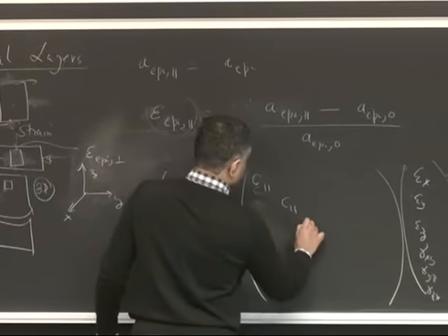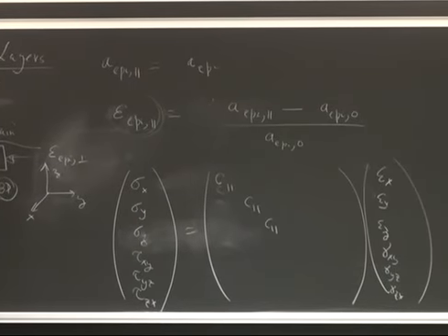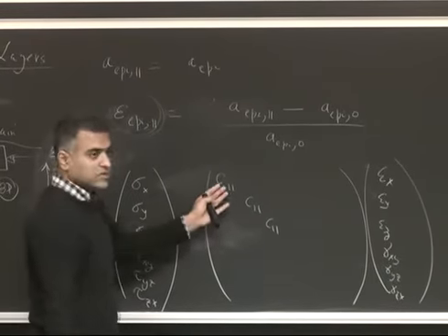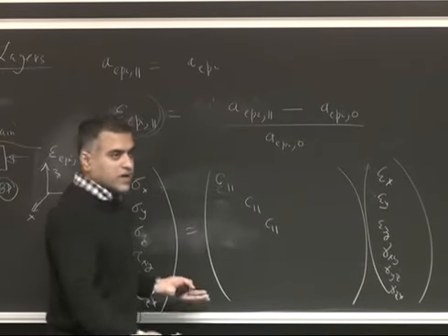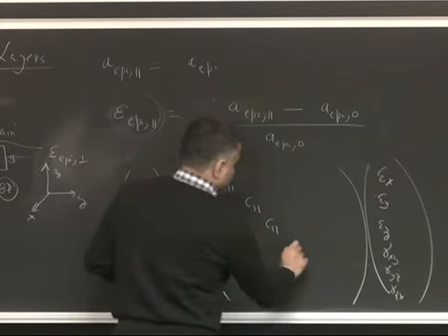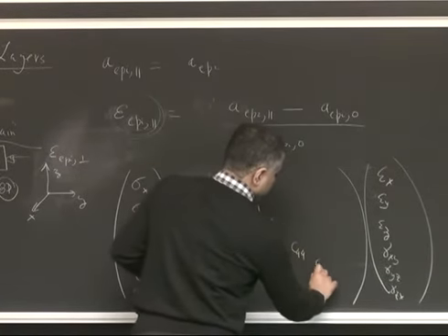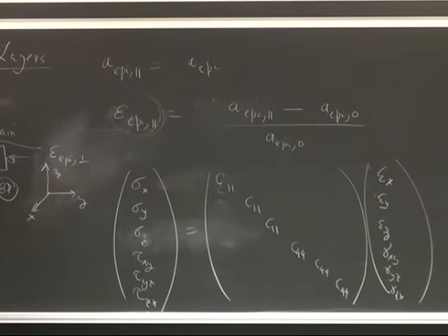The first three diagonal elements will be the same, just C11. Remember, the units are Newton per meter square, a pressure unit, or pascals or gigapascals. Then these three here would be the same as well. The shear components are the same.